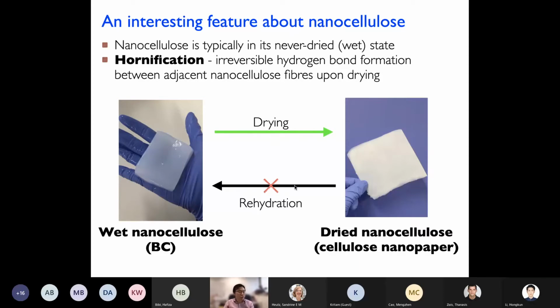So if you try to put this into a dry material, you will lead to drying and hence agglomeration. You need to process the materials wet, but at the end of the day, you have to evaporate off the water. So you're processing 1 kilogram of wet and dry materials with 99% water being evaporated. So your real production rate is actually extremely low in this particular aspect.